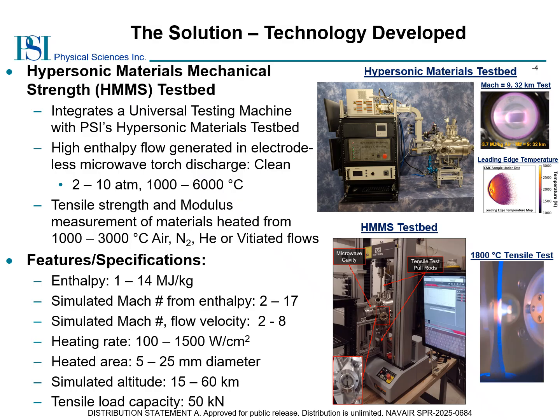The photograph to the right of the HMT photo shows a 1 centimeter diameter test article during exposure to Mach 9 airflow at a simulated altitude equal to 32 kilometers. The image below the photo shows a temperature map of a sample under test measured with PSI's two-color imaging pyrometer that is provided with the testbed. Exposure times in the HMT typically range from 30 seconds to 30 minutes, depending upon customer requirements.